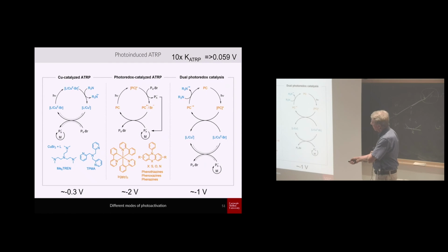These complexes are, in fact, very reducing. They have a redox potential of negative 300 millivolts. Now, you have some other species, especially organic, so some people would not like to use any transition metal. For example, you could use phenothiazine or phenoxazine and acridines. They can be photoexcited to redox potentials in a range of negative 2 volts. So 2 volts versus this one is like 10 to the power 20 or 30 times more active. So they are so crazy reactive when they donate an electron to anything, also to alkyl halides.